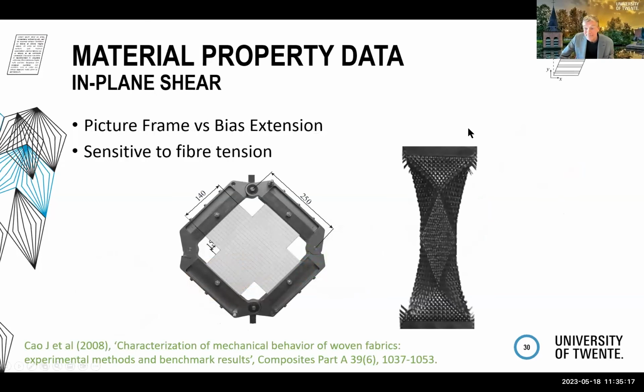Remember, we had these deformation mechanisms, and the first one was in-plane shear. In-plane shear can be measured in various ways. The standard ways would be typically in a picture frame, or by bias extension, so extending a plus minus 45 degrees fabric or fabric ply or laminate in the bias direction and inducing shear, which is inhomogeneous over the different regions in a specimen like that. That's not so much a problem in the picture frame experiment, but the picture frame experiment is very sensitive to misalignment. And if you have a bit of fiber tensioning in this experiment, you're measuring the fiber stiffness more than the actual shear behavior you were looking for.